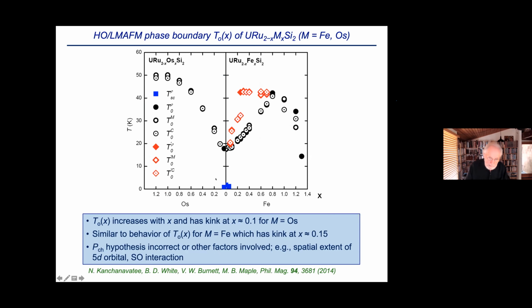But then if you go in this direction, this is for osmium substitution, you see a very similar thing, that rather than decreasing, this phase transition increases as you add osmium. And there's also a kink in this phase boundary at about 0.1. So you have similar behavior for the osmium substitution as you do for the iron.